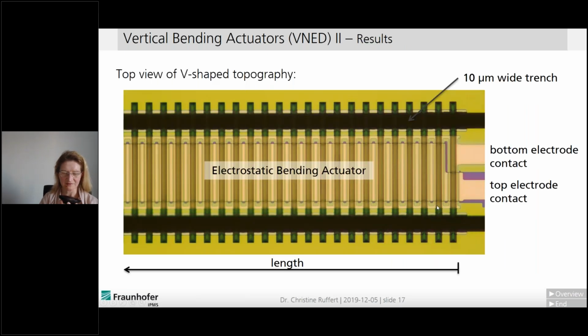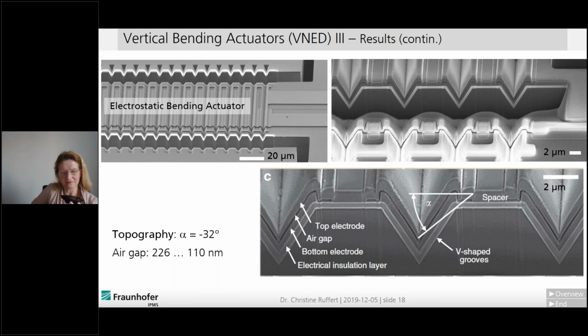So we fabricated the system in the clean room, and here you see a micrograph, a top view of such a system, of such an electrostatic bending actuator. You see the bottom and top electrode contacts on the right hand side. You see the trenches, and this is a type of a VNED, so a vertical bending actuator out of plane. And in addition to this micrograph, I would like to show you some SEM images from a scanning electron microscope.